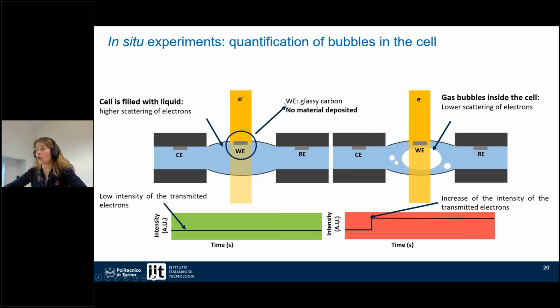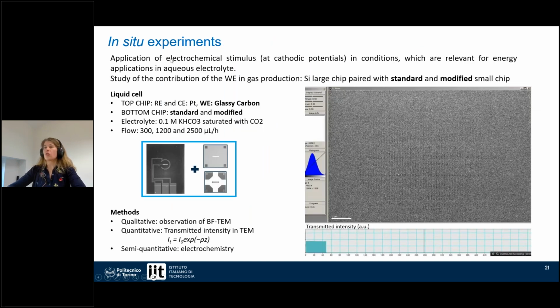So in the next slides, I will show what is happening on the working electrode, which is glassy carbon. We are studying the situation where the material is not deposited on the working electrode. So here we will study the contribution of the working electrode in the gas production when the silicon large chip is paired with the standard or with the modified small chip. As I said, we will have the situation now with the glassy carbon, and the methods of assessment of what is happening there are qualitative observation of the bright field TEM image, quantitative investigation of the transmitted intensity in TEM, and semi-quantitative electrochemistry.